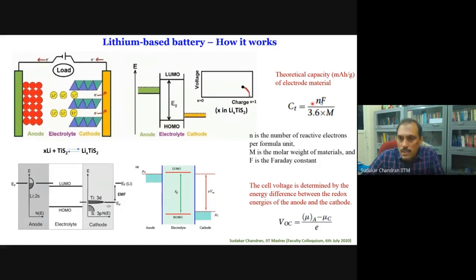Of course, just to point out the theoretical capacity, it's basically how much charge you can store in the anode and cathode. That is given by this equation, where n is the number of electrons per formula unit you can put in. In this case, it is 1 because 1 lithium goes in and out. F is the Faraday constant, and M is the molar weight of the materials. So, of course, you can define the energy density, which is multiplied by voltage, and then the power density, and so on.